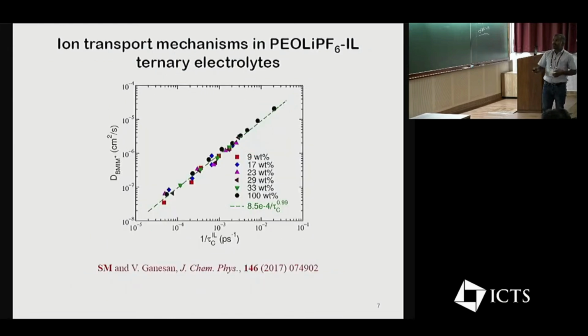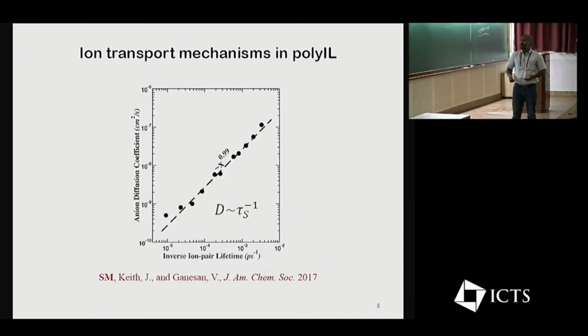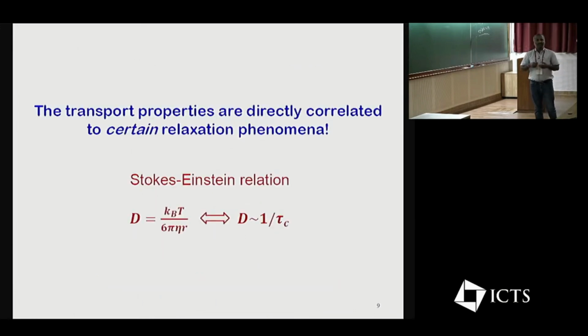Similar behavior exists. Also for a synthetic polymer electrolyte plus ionic liquid electrolyte, which means a ternary electrolyte, you have similar relaxation dictating the diffusion coefficient of ionic species. And in neat polymerized versions of electrolytes, that means pure polymer electrolytes, you also have such behavior. So the point I'm trying to make here is that the diffusion coefficient or the ion transport mechanisms in a variety of liquid electrolytes and polymer electrolytes is directly correlated to a certain relaxation phenomenon. So that's what I wanted to recall.